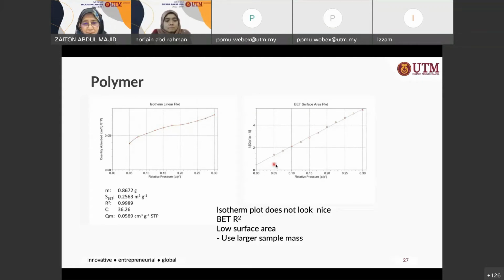Now, when you look at the BET transformation plot from 0.05 to 0.3, the R squared is 0.9989. It's not 0.9999, it's 0.9989. And the S BET is very small, which is 0.2563 meters squared per gram. So one way of improving this data is to try to use larger sample mass in cases where you have very low surface area. You have to make sure that this isotherm, number one, has to increase with increasing pressure. You cannot have the isotherm decrease with increasing pressure. If you have the isotherm decrease with increasing pressure, then something is not right.